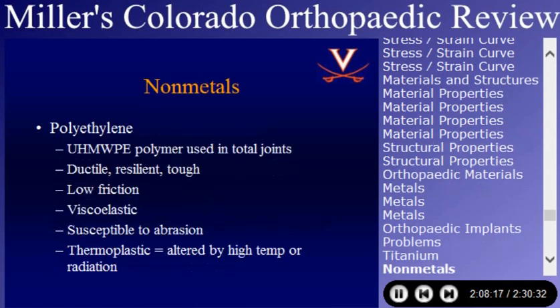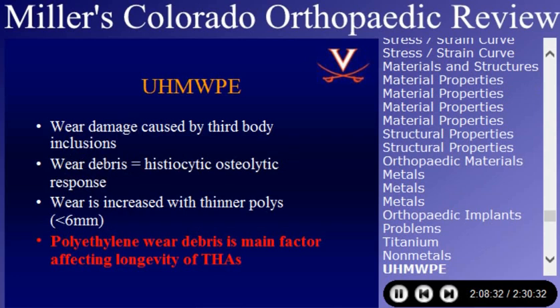Non-metals we need to be familiar with, polyethylene. It's ductile, resilient, it's tough, it has low friction. It's viscoelastic, it's susceptible to abrasion, it's altered by high temperatures or radiation, as I know was discussed in your previous lecture. Polys, wear damage is caused by third body inclusions. There's a histiocytic osteolytic response. Wear is increased with thinner polys of less than 6 millimeters. Polyethylene wear debris is a main factor affecting longevity of total joints.